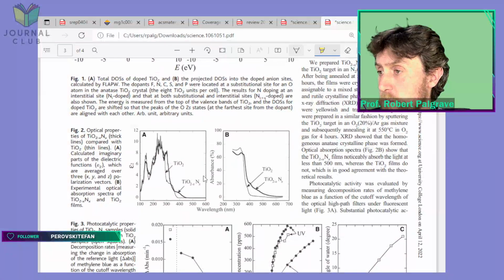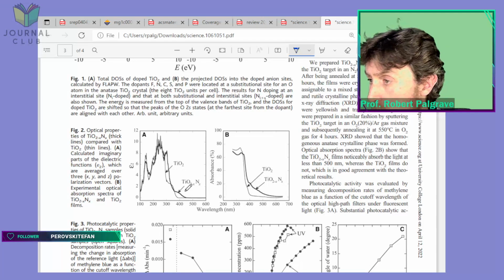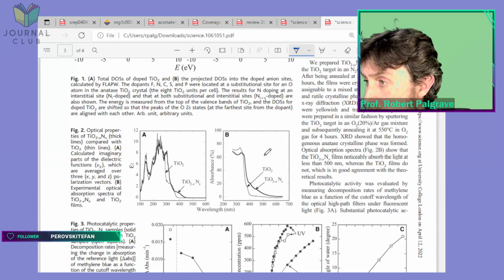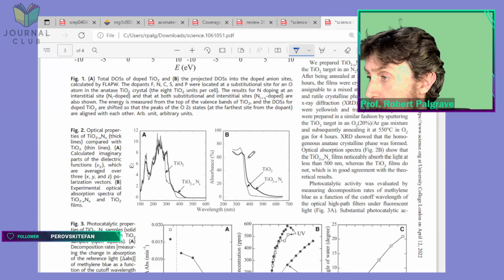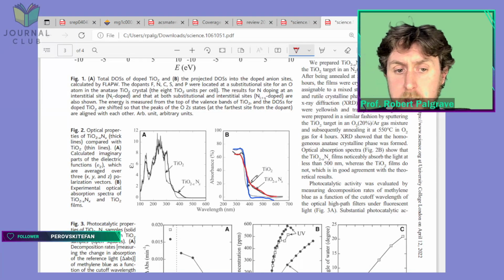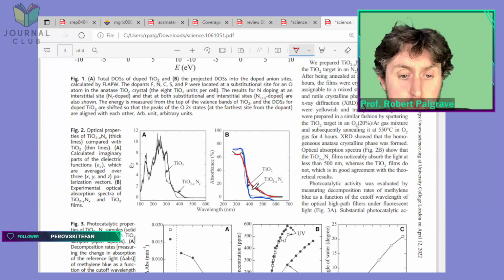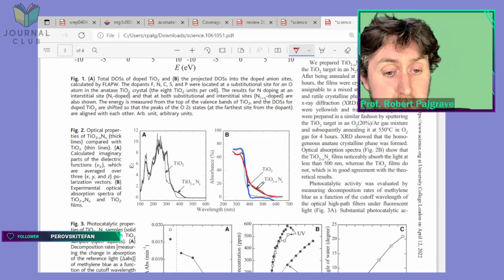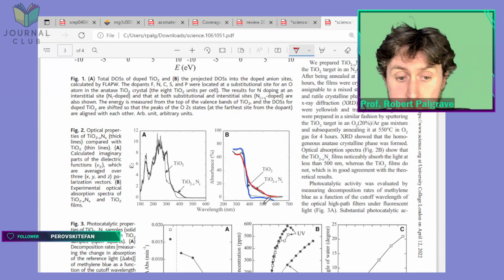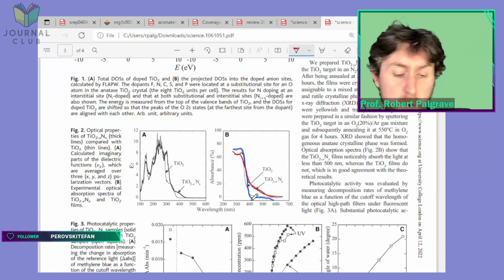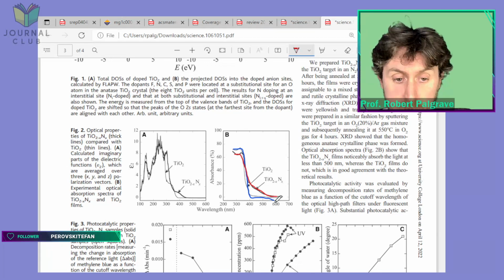They don't even have photos in this paper, but they do have an absorption spectrum down here. And you can see, yeah, so this one on the right here I think is what we want to be looking at. So you can see the original TiO2 material was this one here, and then after you dope it with nitrogen, you get all of this extra absorption here in the visible region. So you're dramatically increasing. This is the visible region here. If you look at the wavelength, 400, 500, 400 is the bluest blue light. 500, 600, this is the green going down into red light here.